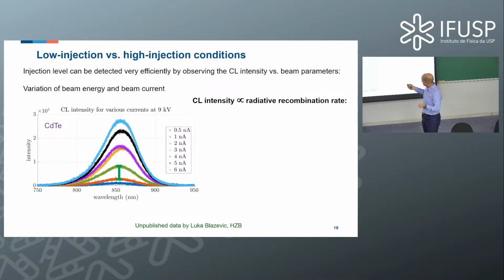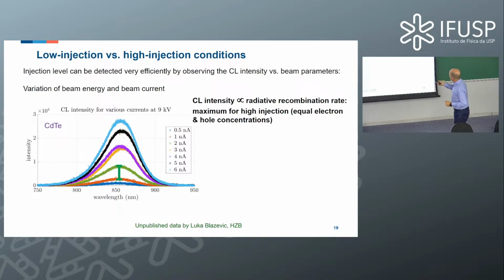Yeah? And if you reach the point where the generated electron hole pairs are equal to the net doping, the number of electrons and holes are the same. So you don't have majority and minority charge carriers anymore. In this case, the recombination rate is maximum because the recombination rate is proportional to the product of electron and hole concentrations. Okay? So this is why it's not exactly an abrupt transition. It's a bit retarded, but nevertheless, if you vary the current of the electron beam, you can see very nicely that there's a transition. Okay, so this is actually the reason why we see this transition. And yeah, the change is gradual and not abrupt, right?